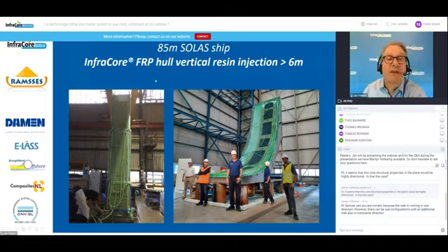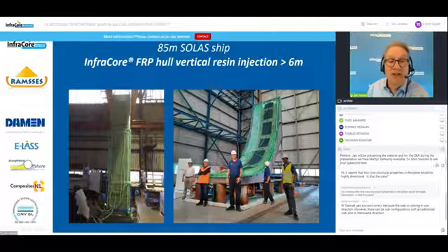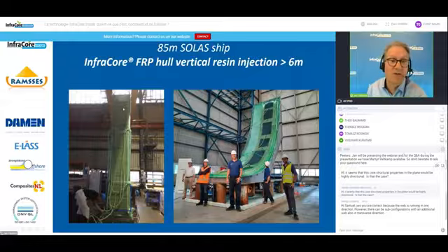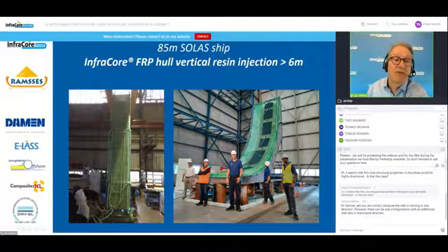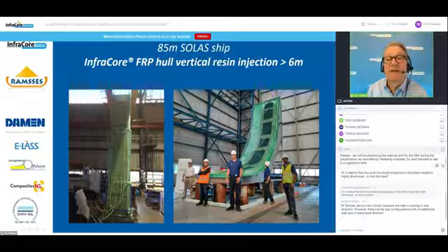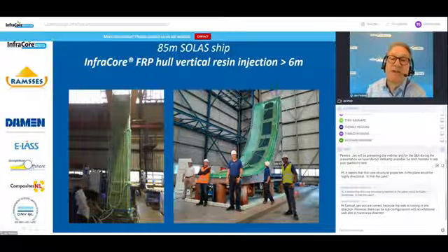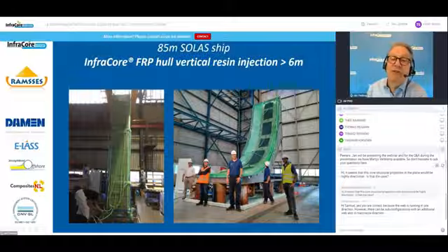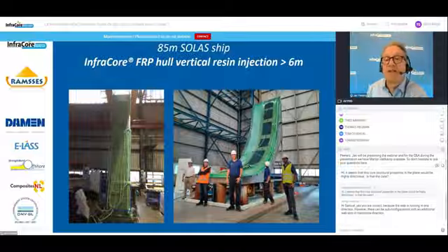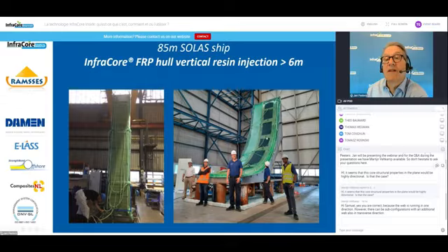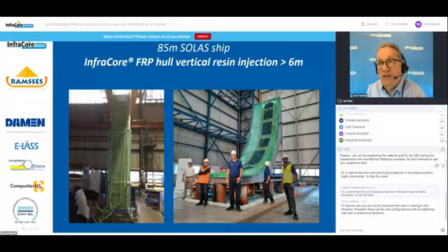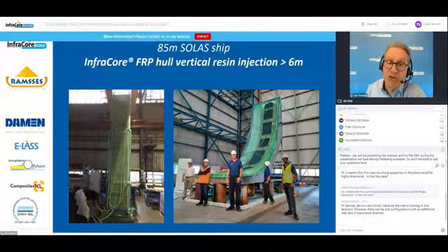Then within the same project, we had to prove that we can indeed inject, for instance, a hull in a single shot injection. And this is the first test for a vertical injection, 6 meters high. We were successful in filling that. And once again, we did that live during a project demonstration event, a live demonstration of an actual injection of an InfraCore skin. And what you can see here is the typical injection. You see that we fill the laminate in thickness direction with injection points. And knowing that this works, the 6 meter high injection tells us that we can inject an 85-meter ship in a single shot. We know how long it will take. We know that the injection will work.